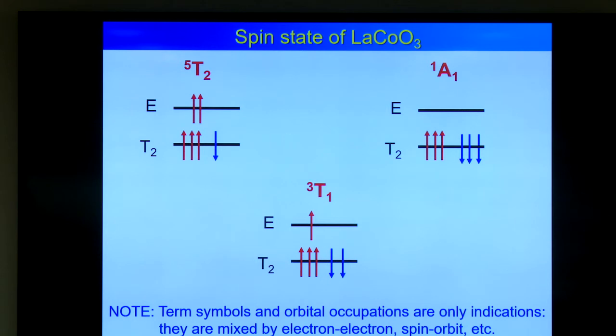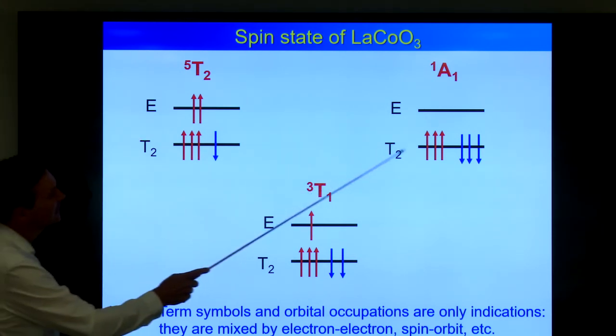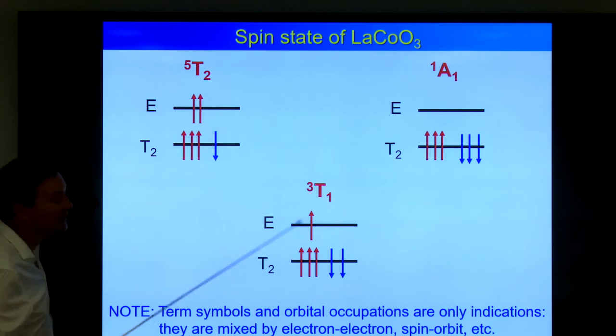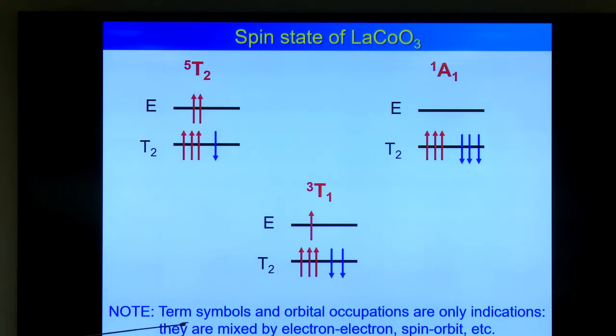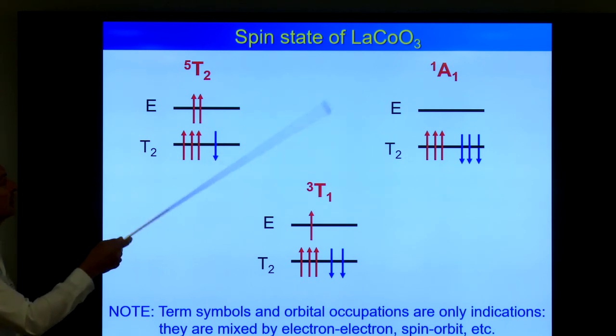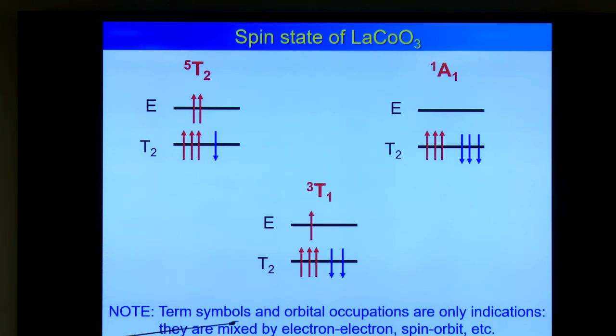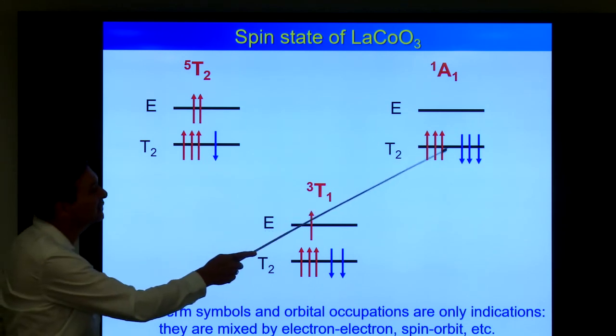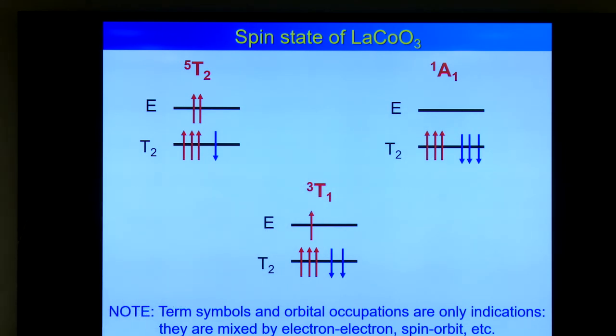the spin state in lanthanum cobalt oxide. It's a very old problem again. There are 3 possible ground states: low spin, high spin, and intermediate spin. Here, just a reminder, the term symbols I indicate here and the orbital occupations are just indications. The real ground state is a linear combination of everything, and will always be a mixture between the different spin states. In a solid, you never get 100% pure singlet A1, it's always a few percent of other states. But let's say we start with this description.